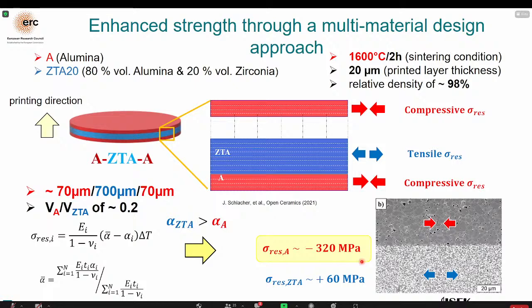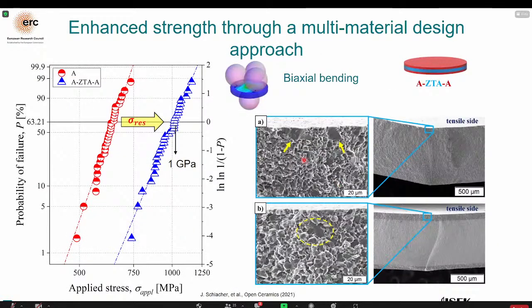If we take a look at the strength distributions again, the calculation says that we reached a strength of more than 1 GPa. And if we compare to the monolithic samples, we can see that the difference is in agreement with the estimated residual stresses according to the calculations you saw before.